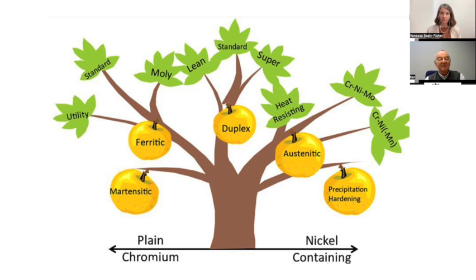And so grades have been developed which contain molybdenum, because the presence of molybdenum in any of the stainless steels helps increase corrosion resistance, or pitting corrosion resistance specifically. This is in line with a particular formula, which there's not a slide to show, so I'm just going to quote it. Your pitting resistance equivalent, your PRE number, is measured by the percentage of chromium in the material, plus 3.3 times the percentage of molybdenum, plus 16 times the percentage of nitrogen in the material. And that's an empirical formula. So we can see the presence of molybdenum in a stainless steel has quite an effect on increasing resistance to pitting corrosion.